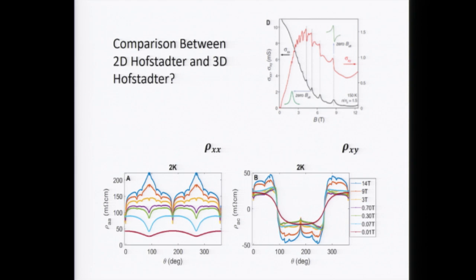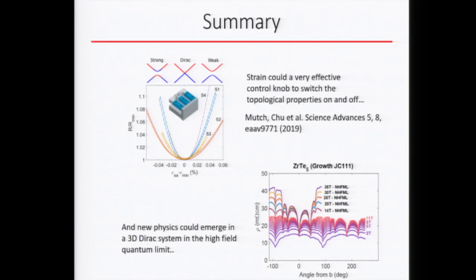Okay, the next slide is my last slide. So in conclusion, we have demonstrated a strain-tuned topological phase transition, and you can find all the details of this work in this publication. We also see very strange behavior in the quantum limit as a function of angle in this material. Thanks for your attention.